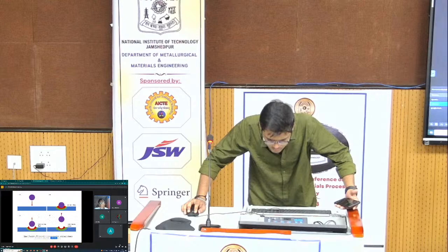We are doing shot peening today with mechanical shot peening, where the steel balls or silicon carbide balls come and impinge upon the surface, and their kinetic energy is known a priori, and then you let them impinge your surface. So there is the red one, plastic deformation, material flow takes place, but there is the elastic spring back as soon as the ball goes back. So you see here the compression. These compressions are giving you the compressive residual stress and higher fatigue strength.